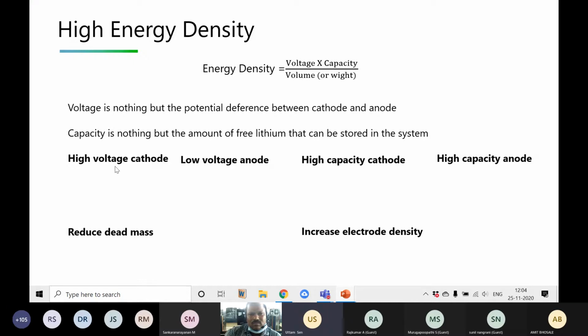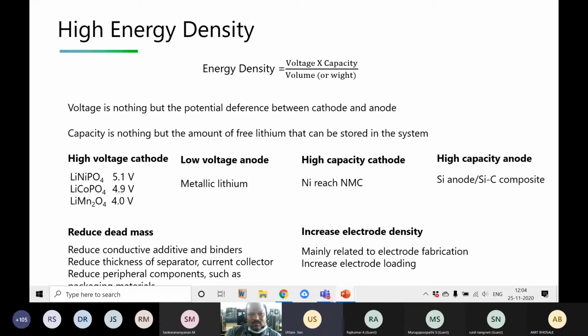Okay. So if you see what promising materials there are for high voltage cathodes: lithium nickel phosphate, which can go up to 5.1 volt, lithium cobalt phosphate, which can go to 4.9 volt, and lithium manganese oxide, which can go up to 4 volt. And for the anode, we are almost at the bottom. Graphite is 0.2 volt. The lowest possible is metallic lithium, where we can get 0 volt for the anode.